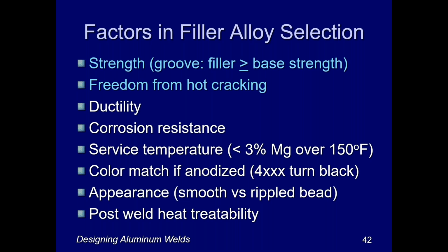First of all, the strength has to be chosen properly. If you're doing a groove weld, the strength of the filler metal has to equal or exceed the strength of the base metal in the welded condition. Otherwise, you're not going to be able to pass that qualification test with that little dog bone specimen, and you can go no farther. The other thing is that the chemical composition of the filler metal and base metal have to be compatible so that you don't get hot cracking. Certain compositions of certain trace or alloying elements can be very prone to hot cracking. In other words, as the weld is cooling from its molten condition, they're very sensitive to cracking, and those combinations just those dogs won't hunt, so they don't work.